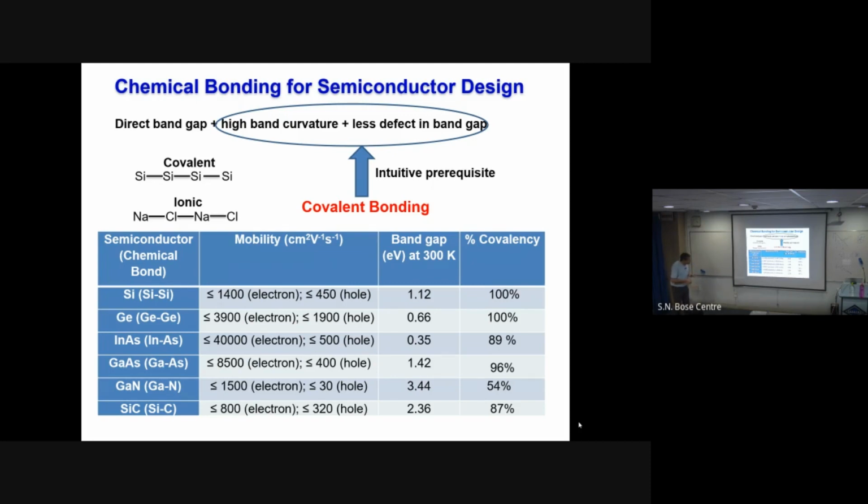After that, of course, I need to go into more detail, for example, what kind of orbitals constitute the valence band and what kind constitute the conduction band. If it is a d orbital, I would expect lesser mobility compared to an s or p orbital. So there will be finer details, and this is just a rough thing to start with. It's not a rigorous thing, absolutely not. Anyway, that affects your whole mobility.